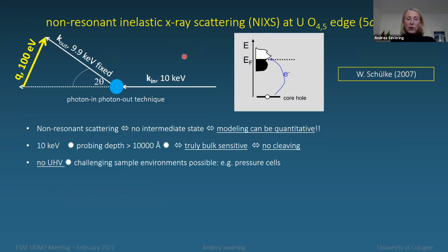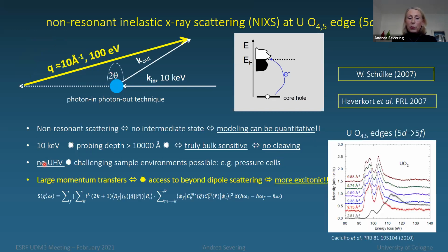Roberto already spoke briefly about the general concept of it. It's a photon in, photon out technique. We do some energy transfer for a core hole excitation, and we are looking here at the 5d to 5f transition, so really probing the 5f states. The nice thing is it's non-resonant, so quantitative modeling is not so difficult, it's possible. We don't need to cleave, because with 10 keV, we are bulk sensitive. We don't need UHV. This is all very nice. But for us, most important is that we can reach the large momentum transfers up to 10 reciprocal angstroms.